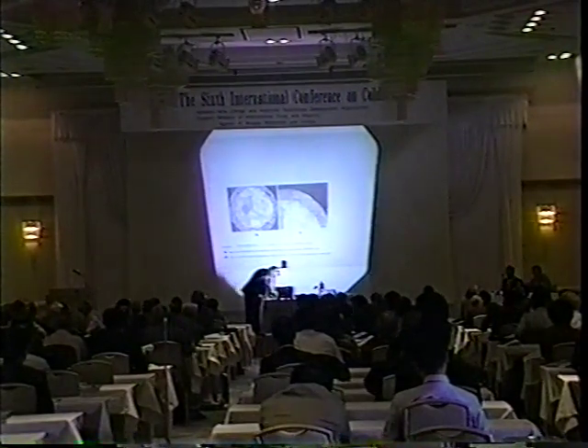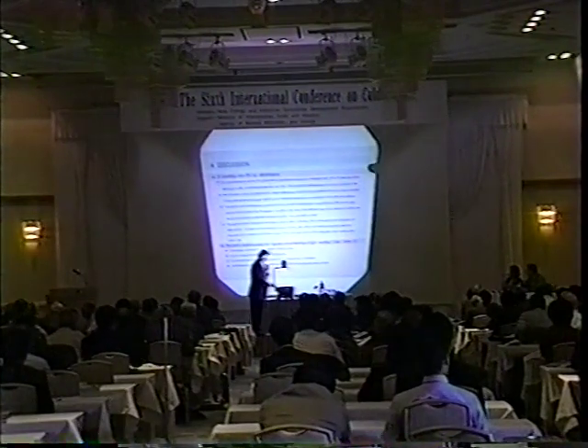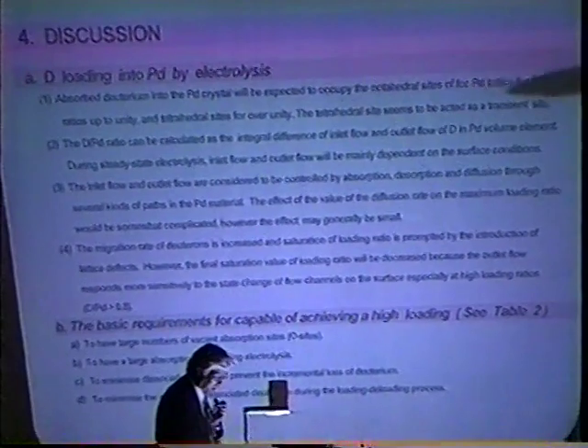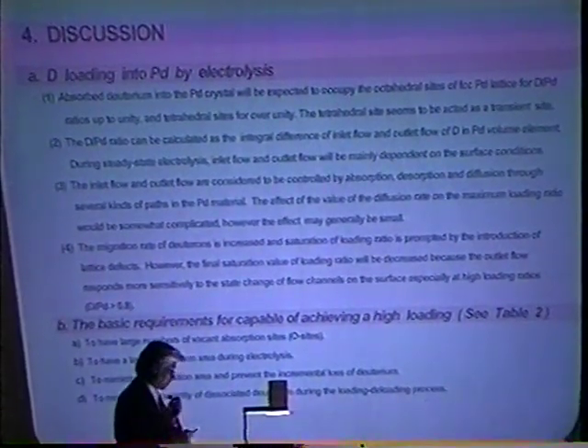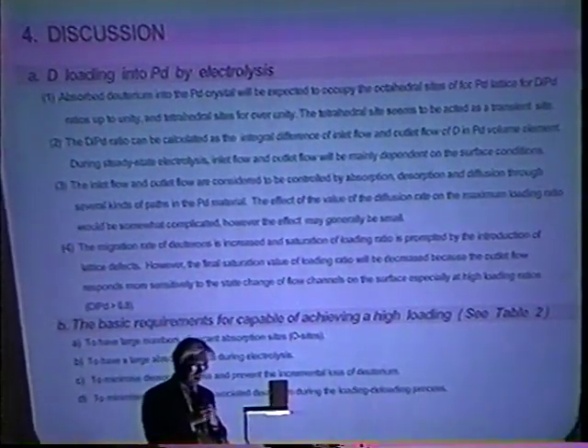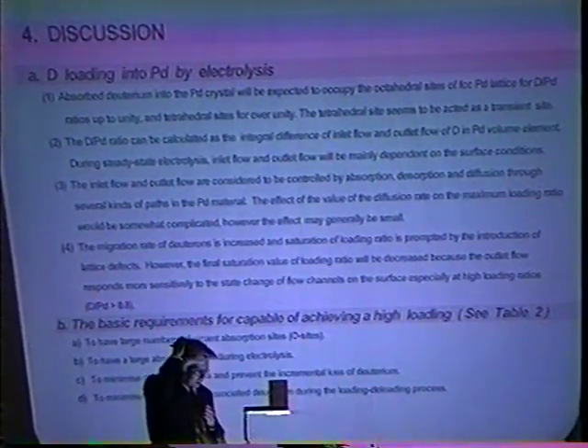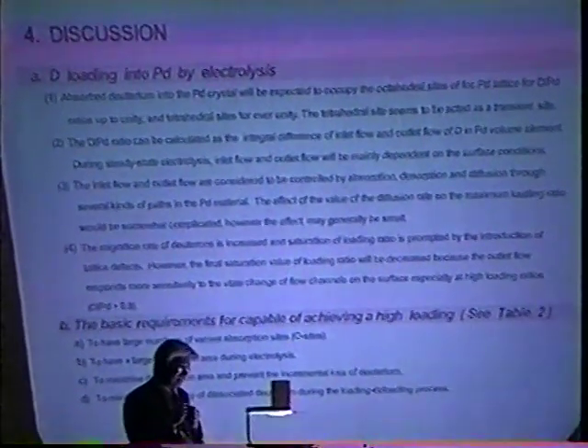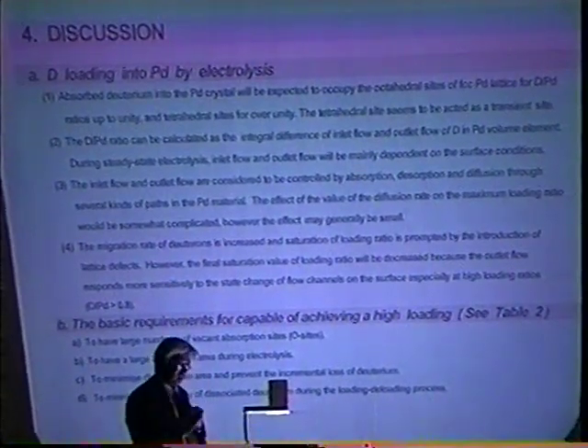I think, as you pointed out, the T site seems to act as a transient site. We measure by pressure in this case. So on average, we cannot measure the local loading. So on average, the loading ratio is not over 1 unit. So I think this site is a transient site.